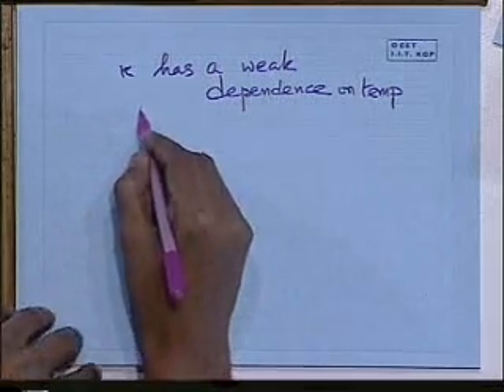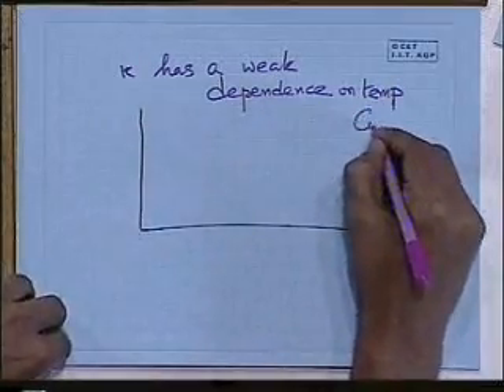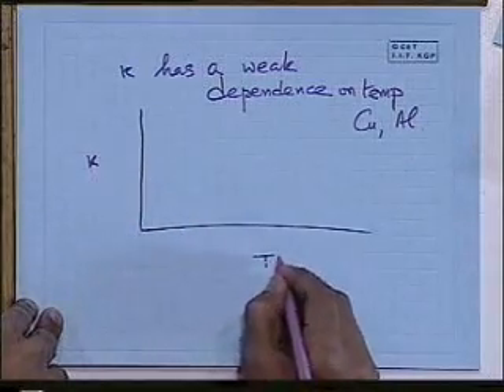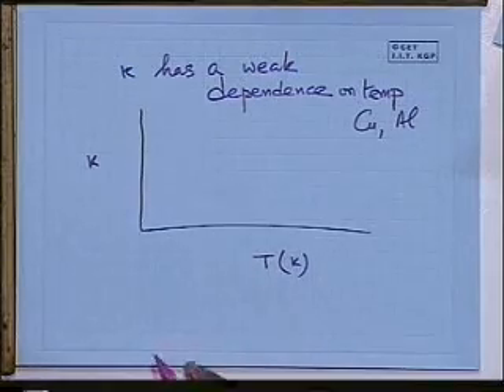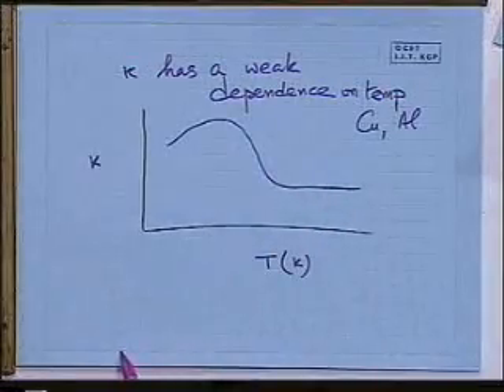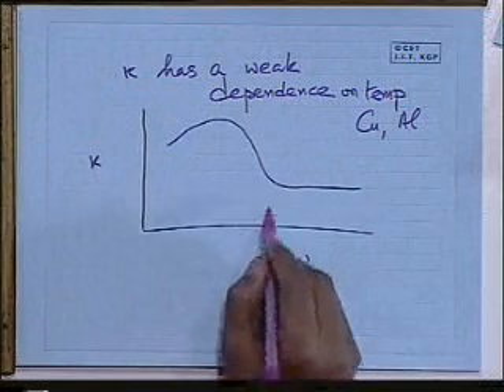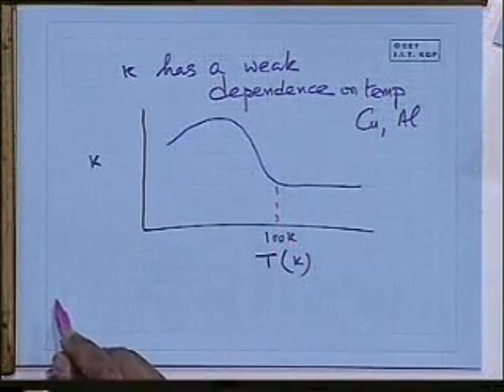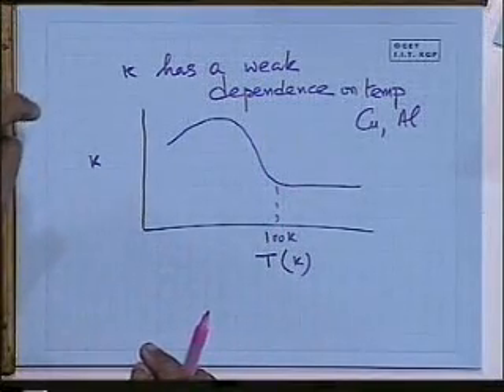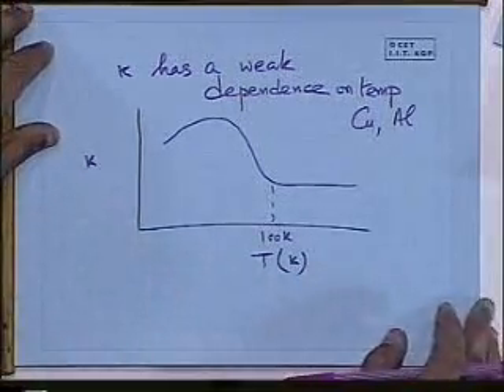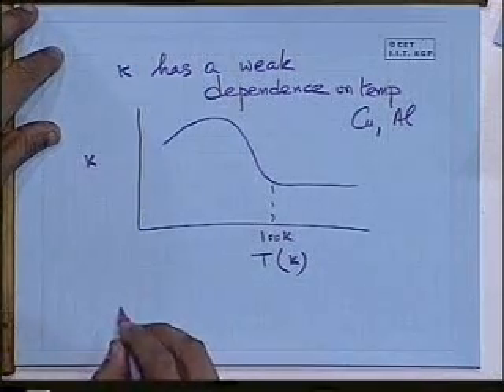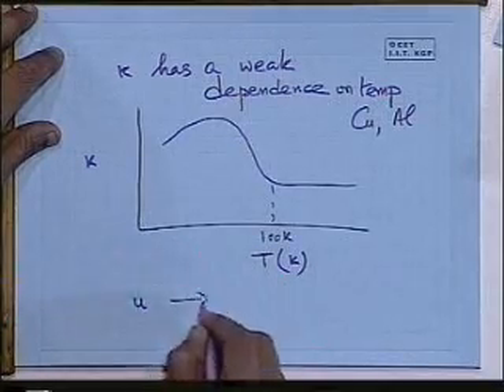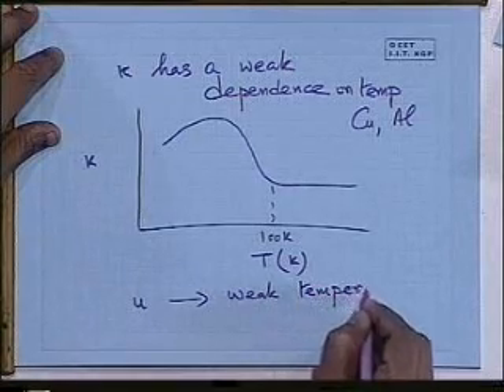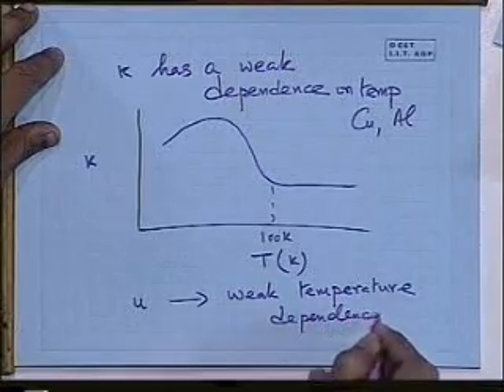And then when we look at experiments, say we take pure metals like copper or aluminum, and we plot kappa versus T in Kelvin. What we observe is a shape something like this. It's not strictly true that it's constant everywhere, but above about 100 Kelvin in these cases, we find that the thermal conductivity is more or less constant. It is related to the fact that the velocity u of the electrons has only a weak temperature dependence. In an earlier lecture we had seen that. So since the energy is being transferred primarily by the motion of the electrons, and the electron motion itself has only a weak temperature dependence, therefore the conductivity too has a weak temperature dependence.